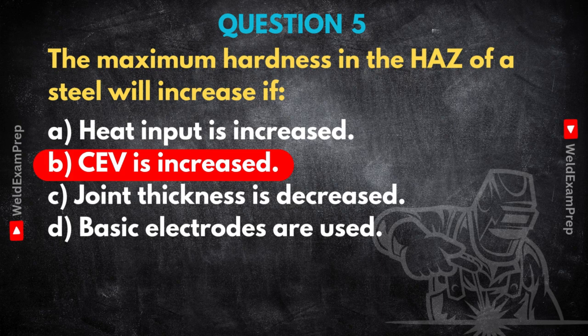That's the chain, yes. Now let's contrast that with option A, increasing heat input. Generally, putting more heat into the weld slows down the cooling rate of the HAZ, right? It takes longer to cool. And a slower cooling rate usually gives the steel more time to transform into softer structures like ferrite and pearlite instead of hard martensite. So higher heat input usually reduces maximum HAZ hardness, not increases it. So the CEV is the direct factor here, indicating an increase in potential HAZ hardness. That's a really important distinction. Different factors pulling in opposite directions.